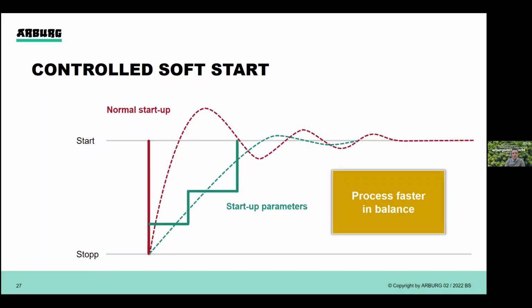Imagine the injection molding machine starting the process, or starting up after a long standstill. The tool is not yet thermally balanced, the filling behavior changes, and the viscosity changes. So the application engineer must fine-tune and change parameters such as the switching point or holding pressure level so that the cavity is not overfilled right at the beginning. Therefore, the multi-stage startup gives the application engineer the opportunity to successfully adjust the parameters shot by shot, in order to bring the process into balance more quickly, as you can see on the graphic shown in the slide.